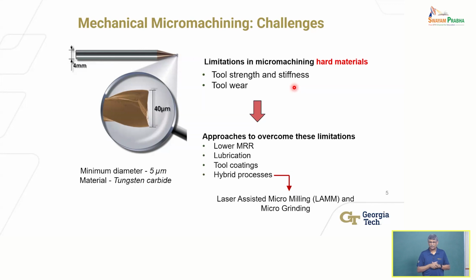Why is strength of the tool a limitation? Obviously, I can make a tool out of cubic boron nitride or diamond, something like that, but that becomes very expensive. They are very hard, and for certain applications they may work, but they're very expensive. So it's not a practical solution. Instead, if I can somehow control the strength of the material that I'm trying to produce these features in, somehow lower the strength in a controlled manner, very locally, then I will reduce the forces involved, and how difficult it will be for me to remove the material is reduced. And that's the approach, that's the idea. So one way to do that, as you know, certainly for metals and including for ceramics, what happens to the strength of the material when you heat it?